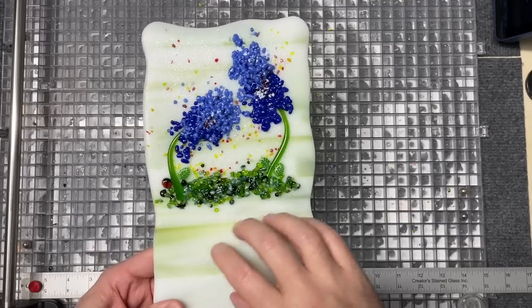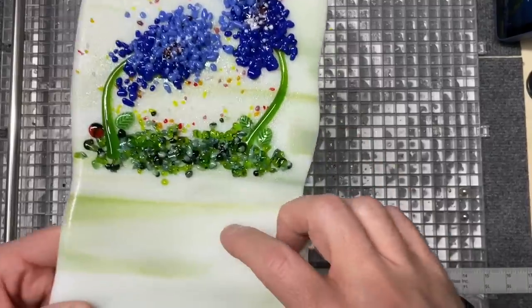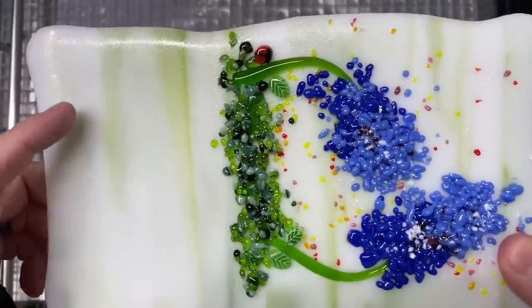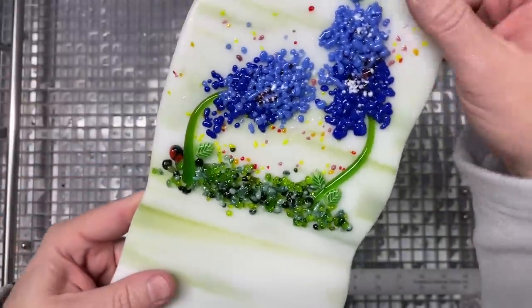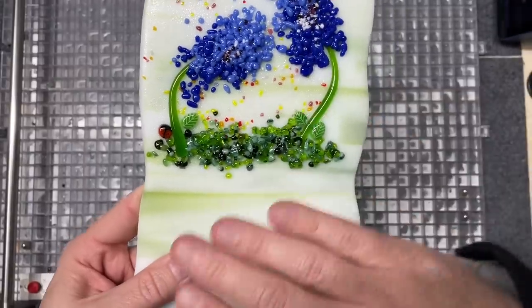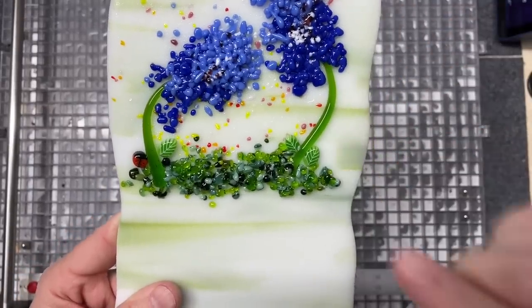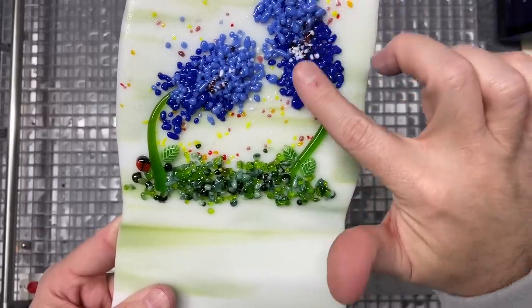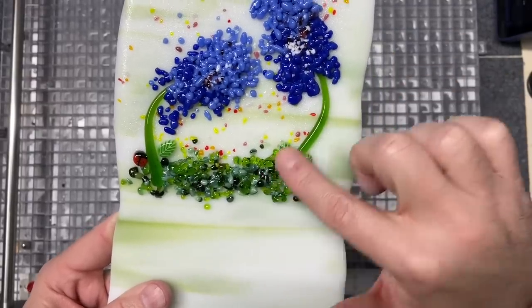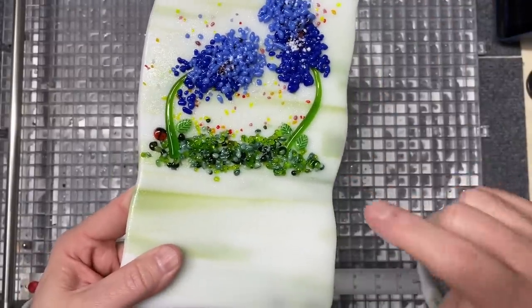Here's the other scrap glass piece — the same interesting phenomenon happened here. I dusted the entire thing with clear powder and got some interesting texture where it was starting to devitrify. That clear powder actually almost enhanced the texture. It was all in the same kiln load, and the clear powder didn't do that on anything else — only on the white pieces prone to devitrification. These other elements here fired nice and the clear blended right in. This is going to become a self-stander — I'm going to slump it on a mold, so stay tuned.